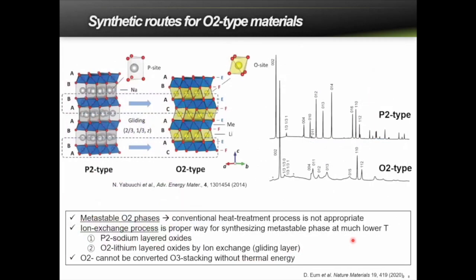So inspired by this idea and the theoretical calculations, we decided to synthesize the O2 lithium excess layered structure. But unfortunately, we could not obtain the phase using the conventional solid state reaction, because it's not the thermodynamically stable phase; at high temperature it is O3. So we had to go through an indirect method.